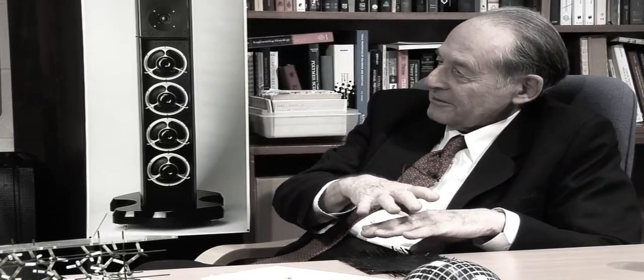What happens here, yes, is that if you take a sheet like this, close to its melting point, the trick is that the surface of each of these individual elements has a slightly lower melting point than the bulk interior. So, believe it or not, you can melt a thin skin on the surface of every element here, quite uniformly. So you then cool it down, and that freezes and forms the matrix. So you start off with a whole lot of fibres that are not connected in any way. You heat it up just below its melting point, a skin forms, which melts. You cool it down, and that freezes, and then you've got the whole of this with a matrix of that skin, which is fantastic. And that's the trick. And I think it wasn't really appreciated that this would happen.